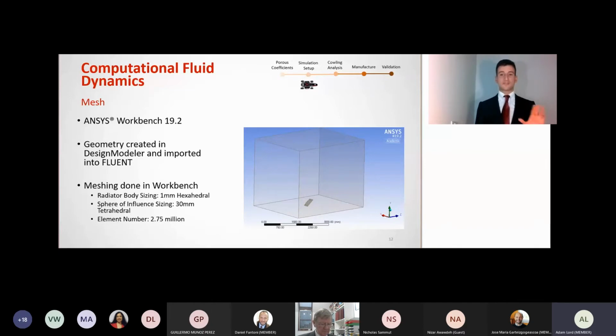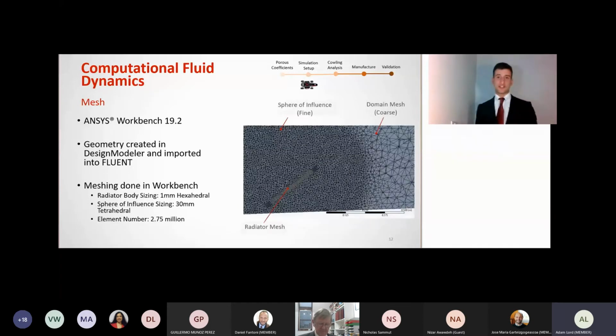Now, this setup was first meshed in ANSYS Workbench, where a fine hexahedral mesh was used for the radiator itself, with a sphere of influence surrounding the zone which was deemed to be the most crucial for us. Using a sphere of influence to mesh this localized zone was actually very helpful in this case because it allowed for the creation of a much finer mesh to better capture fluid behavior around the radiator. And the accuracy of the mesh was validated through a grid-independent study, but also a domain-independent study was carried out to ensure that the size of the fluid domain used was sufficient to capture the entire behavior of the flow.